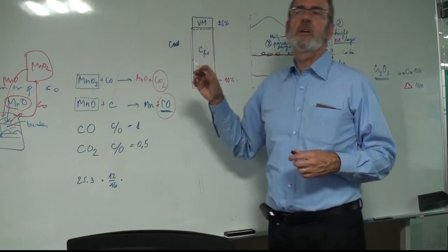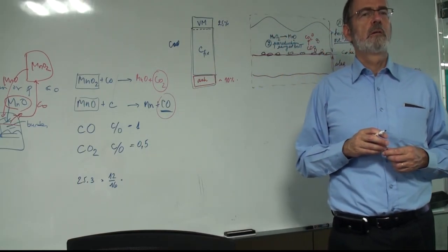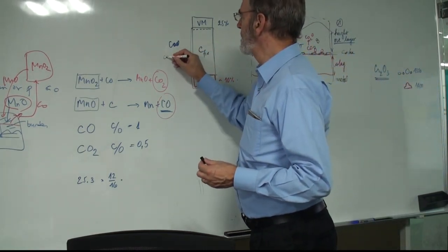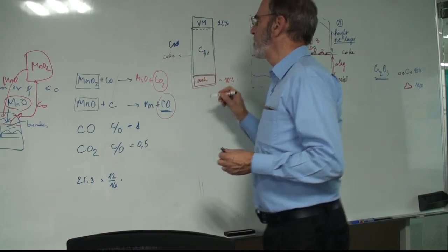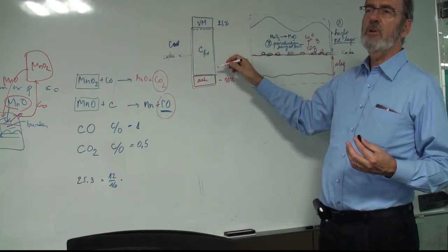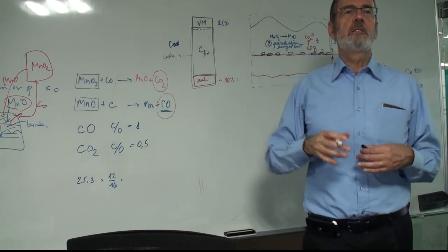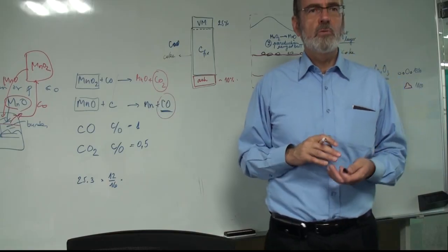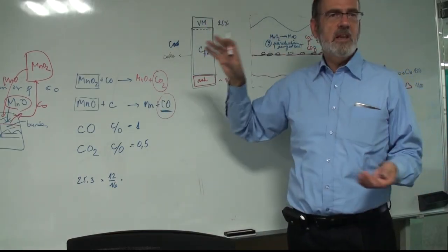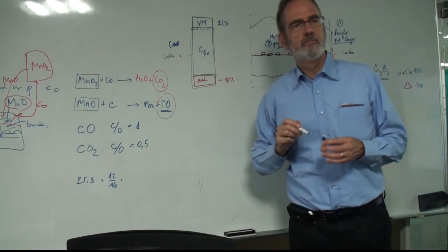So when heating the coking coal, the specific coal giving coke, you fabricate coke, which has practically only the fixed carbon, no volatiles, because you have heated in the coke oven plant up to 1000 degrees, and all the volatiles escape, and you have the fixed carbon, and you have the ash.